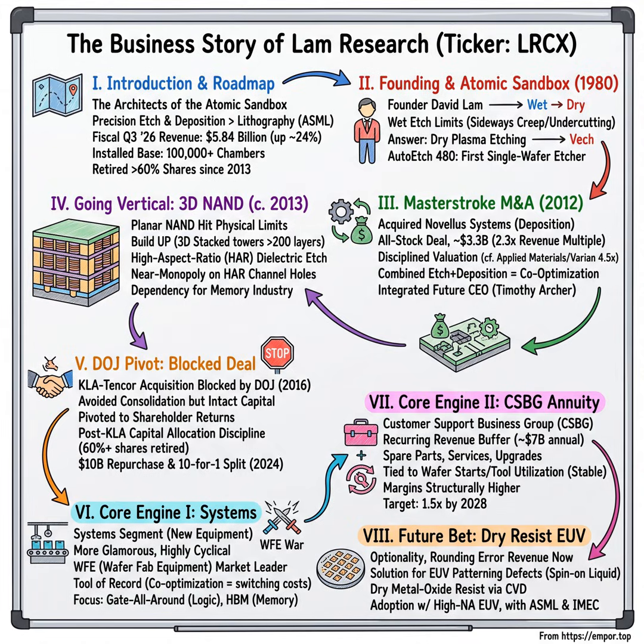The second transition is in memory, the explosion of high-bandwidth memory for AI accelerators, where HBM3E and HBM4 require deep through-silicon vias, vertical tunnels drilled through the DRAM dies so they can be stacked, which demands exactly the kind of intense, high aspect ratio dielectric etch that is Lam's signature strength. AI, in other words, is not an abstraction for Lam. It shows up as physical demand for the hardest holes in the industry.